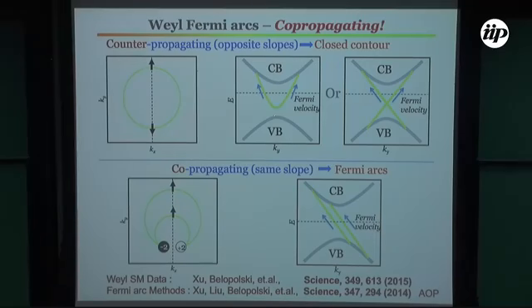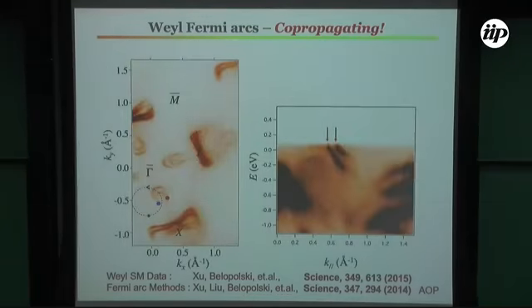If I'm looking at, say, Rashba surface states, then I have counter-propagating states at the Fermi level. Or if I'm looking at topological insulator surface states, same thing, I have counter-propagating states. There are pairs of Fermi velocities possible. But if I have a co-propagating state, then if I look at the energy dispersion, they should be co-propagating. Only this type of co-propagating states will tell us there's a non-closed Fermi surface. This is not possible with a topological insulator Dirac surface state, or Rashba, or any other surface state. So we have to check in the energy axis whether the states co-propagate or counter-propagate.